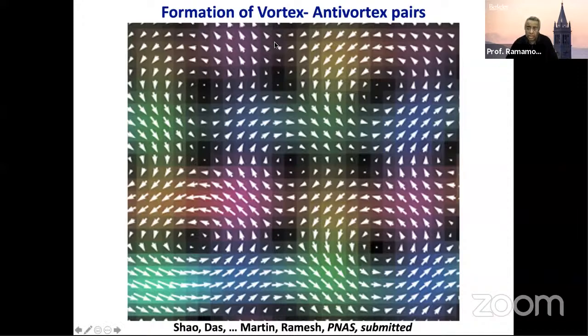The other thing that you see is that they now start to form anti-vortices. You have an anti-vortex here, here, and here. And that's really an important thing because so far we had never seen these in the dipolar systems. And so there is evidence that there is some kind of a topological phase transition that's happening. So this work David has just submitted to PNAS a month or so ago.